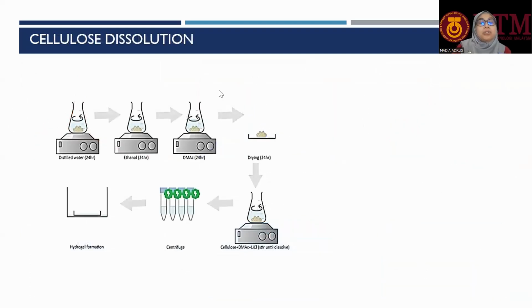Next, I would like to show you that cellulose can be further processed via dissolution, which involves several pre-treatment steps: swelling in water, in ethanol, and also DMAc, which stands for dimethylacetamide, for 24 hours each. Then it is subjected to drying. After that, these samples are dissolved in dimethylacetamide plus lithium chloride and centrifuged prior to hydrogel formation.